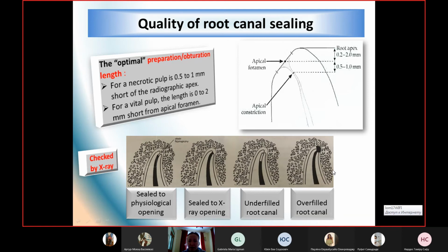And here you have such a schematic representation of root sealing. Sealed to physiological opening, so it's okay. Sealed to X-ray opening as well, it's okay if it comes to necrotic pulp. Underfilled, pay attention, not enough root sealing, and overfilled, like too much, it is in periodontal tissues. Of course, this can be checked by X-ray. The quality of root canal sealing is normally checked by X-ray after root sealing.